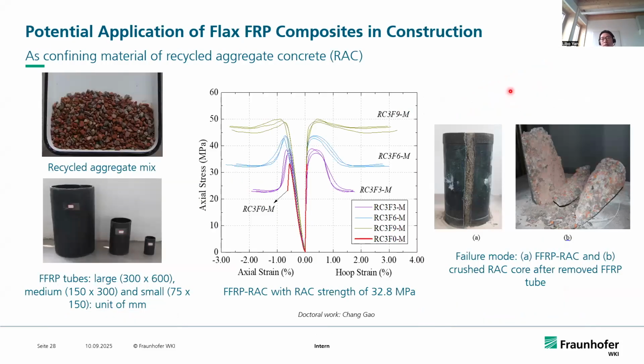We know recycled aggregate concrete is a sustainable approach if used for new construction applications. However, compared with normal aggregate concrete, recycled aggregate concrete normally has much lower compressive strength and shows larger variation in the compressive properties. So by using the flax FRP tube as extra confinement, we will be able to increase the compressive strength and the ductility of the concrete significantly, and also reduce the variation, as you can see from those results.